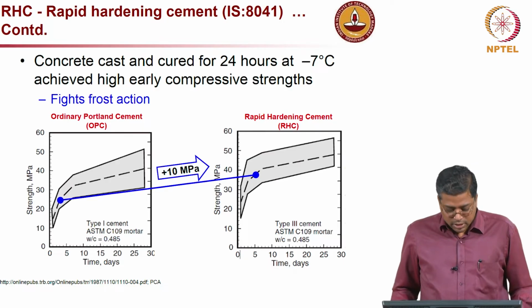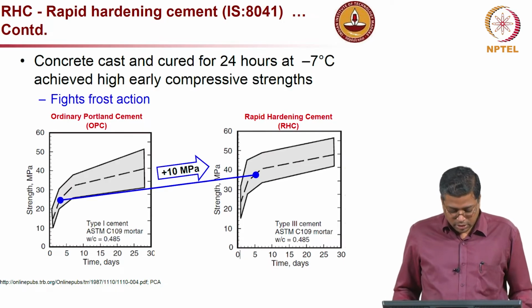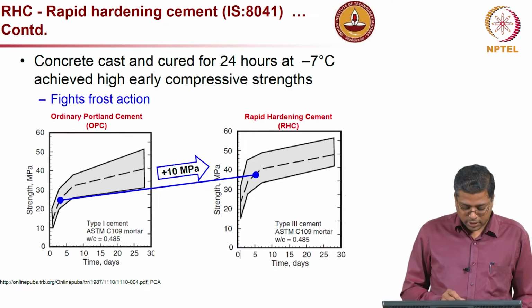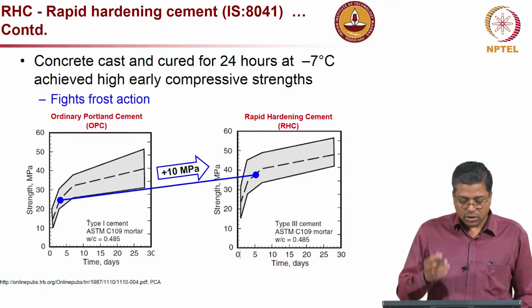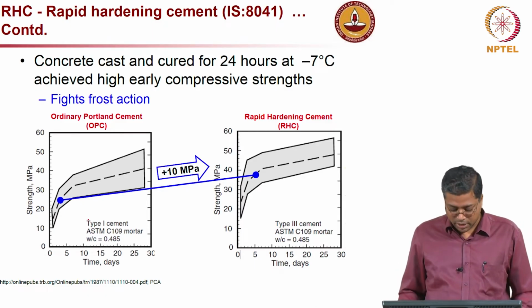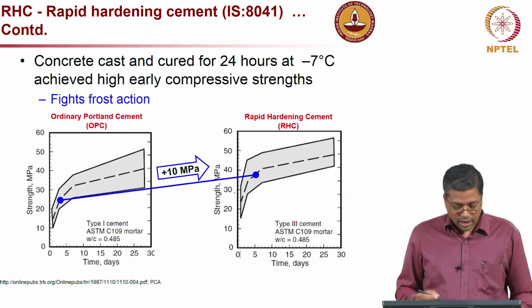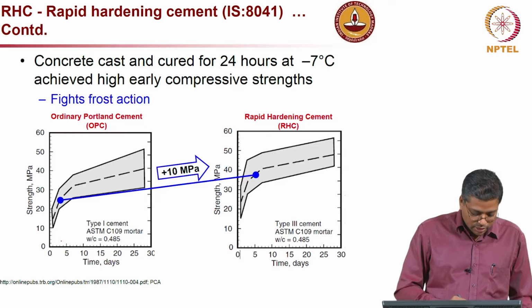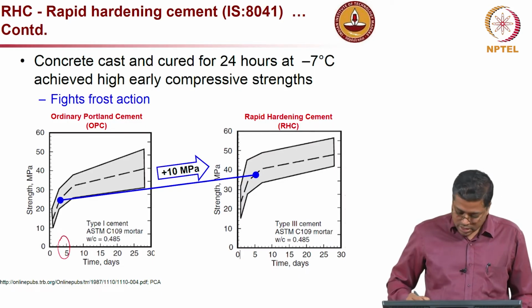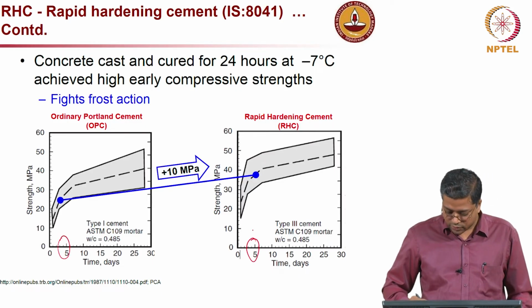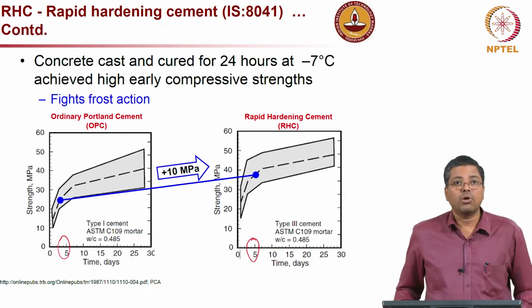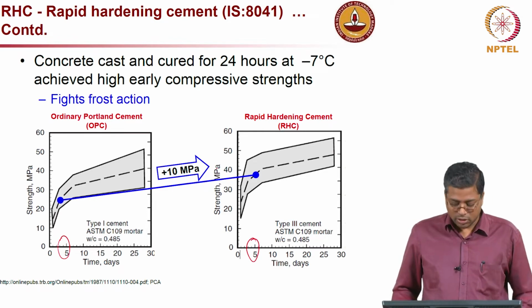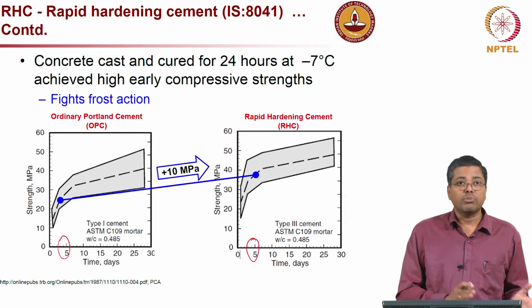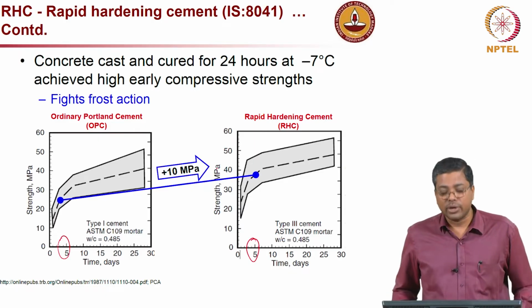Now, this graph shows how the use of rapid hardening cement can help in increasing the strength gain in the early period. Let us look at about 3 to 5 days. You can see that there is about 10 MPa strength gain when you compare OPC to rapid hardening cement.